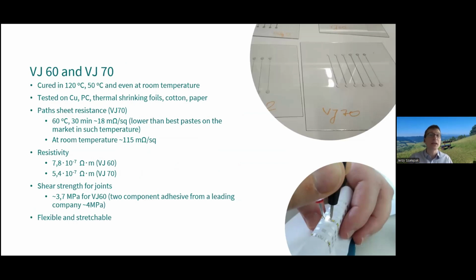A few years ago, we needed a material for an adhesive for thermal shrinking foils. The issue was that instead of 70 degrees, the thermal resistance of these foils was 50 degrees. Even 51 was already too much, and the substrates would break, shrink, or deteriorate. So we covered over 50 different variations of adhesives, polymers, particles, residues. We tried UV-cured ones, chemically cured ones, etc. And there was always some issue, whether it was conductivity, brittleness, or just mechanical bendability.